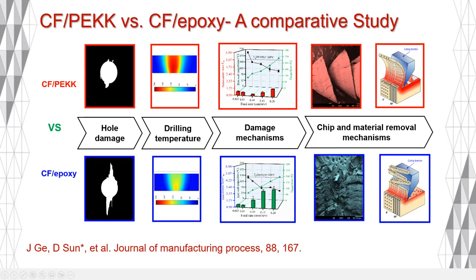Given the temperature sensitivity of the thermoplastic PEKK matrix within the composites, we carried out further investigation into the machining temperature evolution during the drilling process and looked at the effect of temperature on the associated material damage. We also carried out a detailed comparative study with the thermoset carbon fiber reinforced epoxy composite and revealed the significant difference in the drilling performance between these two composite systems.